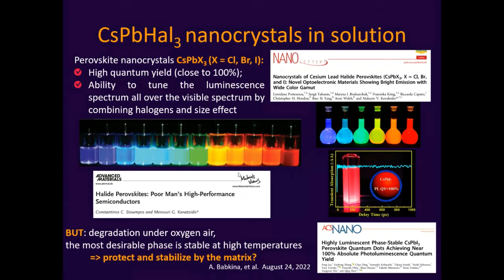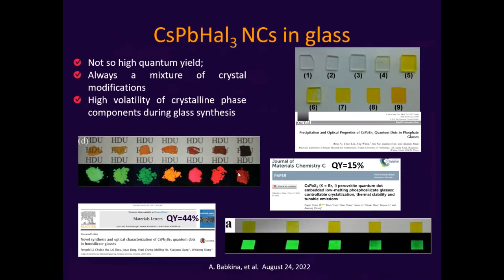The first idea was to stabilize them by polymer matrices. I'm not working with polymers, so I liked the second idea, to stabilize these nanocrystals by the glass matrix. And starting from 2016, such papers arise. The first paper just showed us the possibility that these glasses with such nanocrystals can be made. And of course, they were made, and you see them here, the first one, inside of the phosphate glass matrix. But quantum yield was not mentioned by the authors.